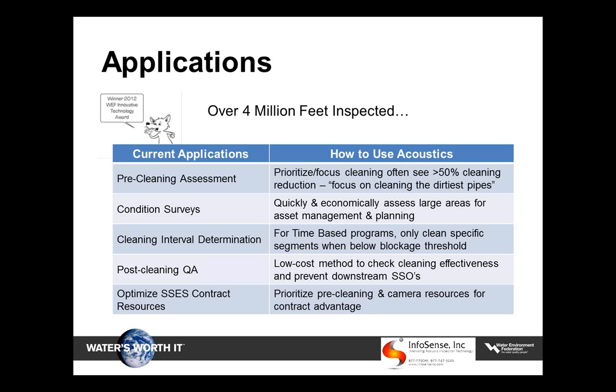The city of Augusta, Georgia encountered a situation where they had a 36,000-foot basin that was prioritized for cleaning due to customer complaints of low flow. To clean the basin would have cost approximately $40,000 with an outside contractor. Without the SL-RAT, that's what they would have done. But with the SL-RAT, their crew was able to inspect the entire basin acoustically in approximately 3 to 4 days. What they discovered was there was only about 2,200 feet of pipe that actually needed cleaning. So they were able to deploy their own equipment to take care of the problem, and the savings from this one situation essentially paid for their